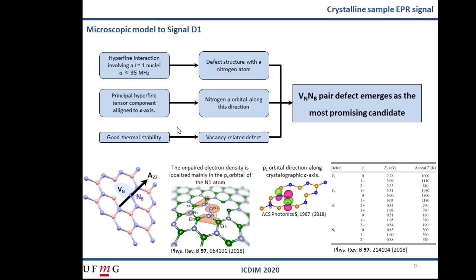In its neutral charged state, it is characterized by a spin 1/2, whose wave function is distributed in the pz orbital of the nitrogen antisite. Here, for example, this is illustrated. In agreement with the experimental data, it is predicted that this pz orbital is parallel to the c-axis direction. So, this agrees with what is observed in the experiments and what is proposed by theory. The good thermal stability could be a consequence of the associated nitrogen vacancy of the defect, since isolated vacancies are predicted to be stable even when exposed to high temperature.